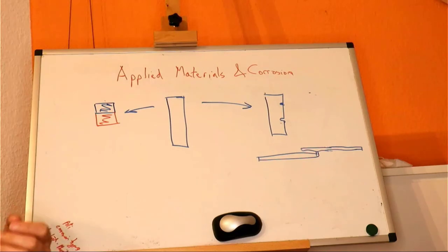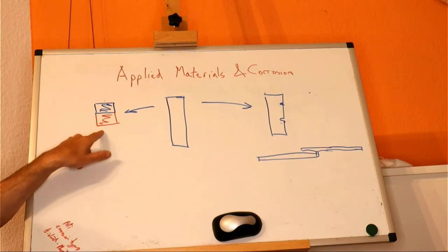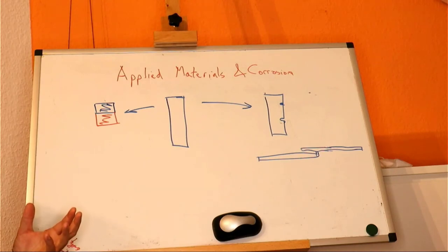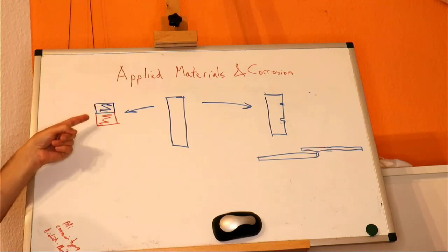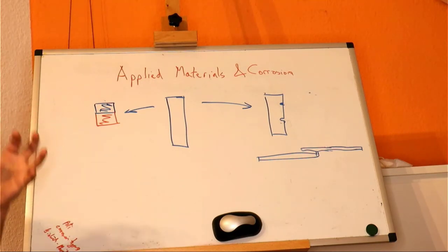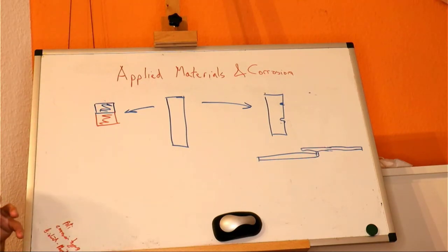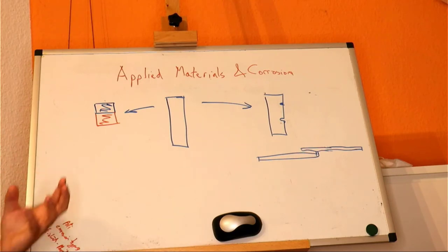So if we take the first couple of types of corrosion, we can imagine two different metals. It's the simplest type of corrosion that we can imagine. And we can look at a video that I've put on this course last time, where I took a piece of platinum and a piece of tin. Tin is above the hydrogen line, as long as it's slightly acidic. So if we take acid and we put tin in, we would expect it to dissolve, forming hydrogen, but it doesn't, because there's a high overpotential, because there is a high energy barrier to hydrogen formation on tin.